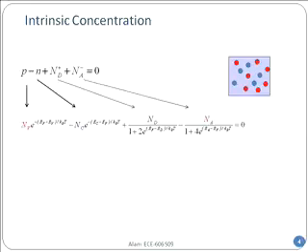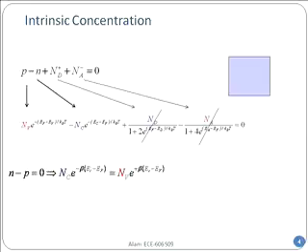For example, one thing we said is that if a material is undoped, then I should not have any donors or acceptors. So those terms are gone, and only the first and the second term remain. N minus P equals 0. I can equate them and solve for the Fermi level EF. And once I solve them, this is exactly the expression we did before.